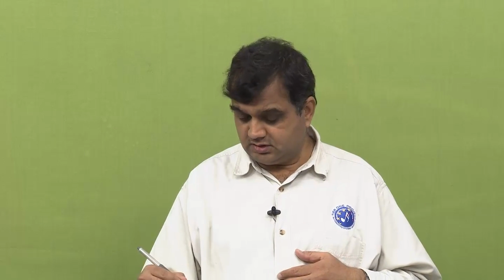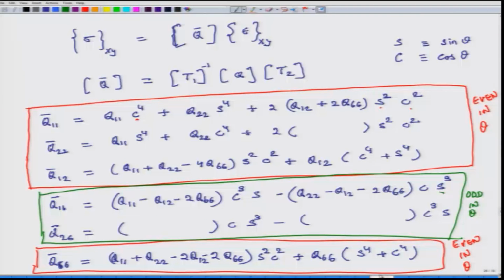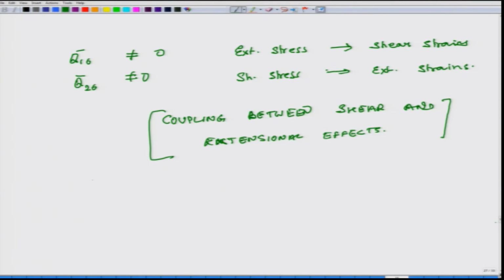So, whenever we measure theta, this is the convention we follow, otherwise we will not get our shear strains and things like that, or we will not get our solutions correct, okay, because of the sensitivity of Q16 bar and Q26 bar to the direction of theta. So, we should be clear on our conventions which are consistent with the conventions we have used in this formulation.